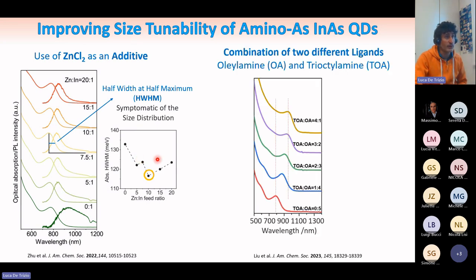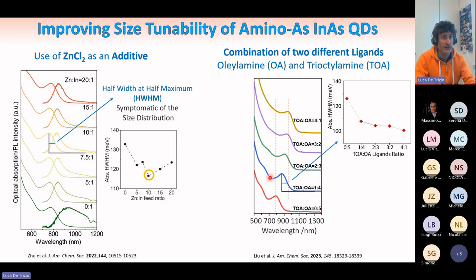In yet another work, what we did was to combine the typical ligand employed in this synthesis, which is a primary amine, with the tertiary amine that you can see here. And the combination of the two led to these kind of samples. As you can see, the absorption peak is a bit shifted, meaning that the size is not exactly the same. These are larger than this. And again, if I judge the width of these curves, what I can see is that employing the combination of the two ligands, again, we got an improvement in terms of size distribution control.